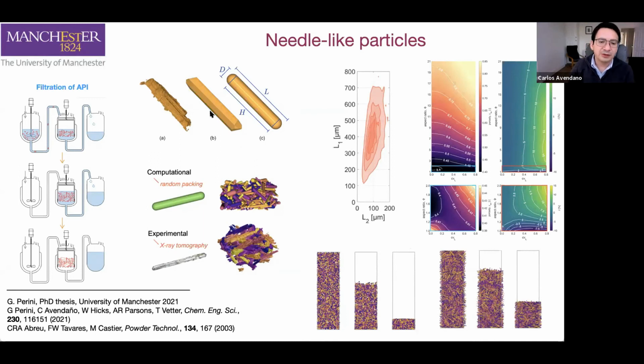And we decided to do the following experiment. We know that these filter cakes are formed by this type of crystals, this type of needles, but they have different size and shape distributions. That's something important in the pharma industry: what is the typical length and diameter of these particles? A typical size and shape distribution of these particles will look something like this, where in the x-axis you have the dimensions for the width of your particle, and in the y-axis you have the length of the particle. So this is the type of distribution that you have, where the mean or the average aspect ratio is here at the middle.